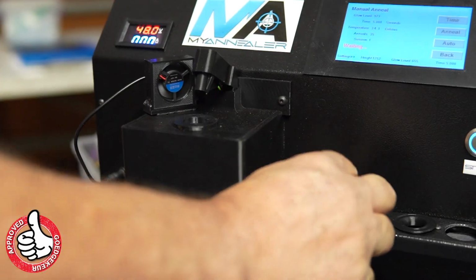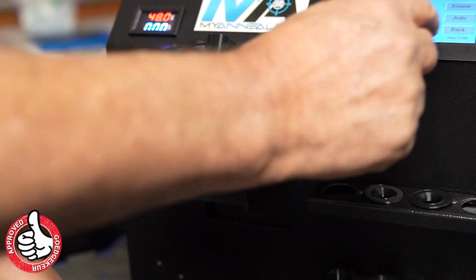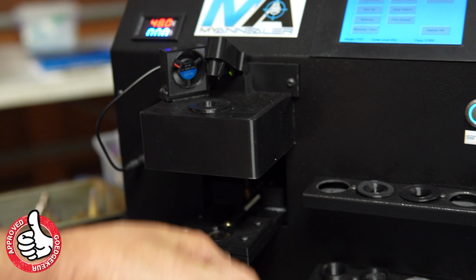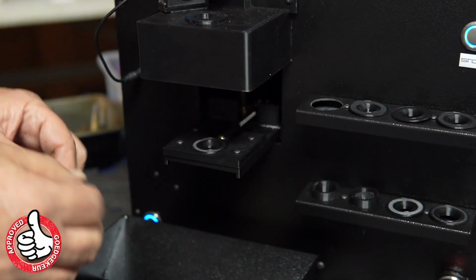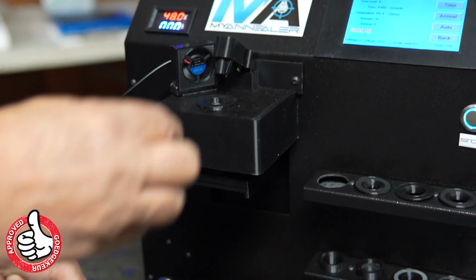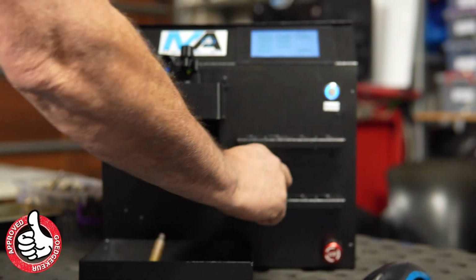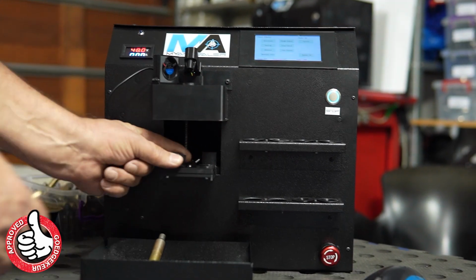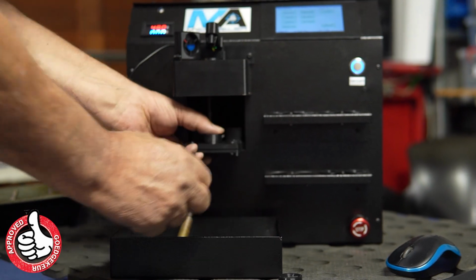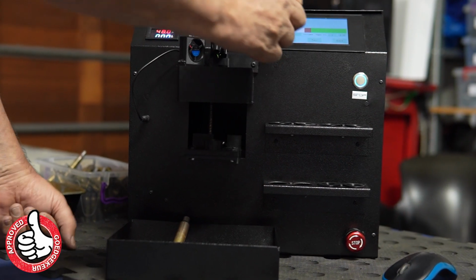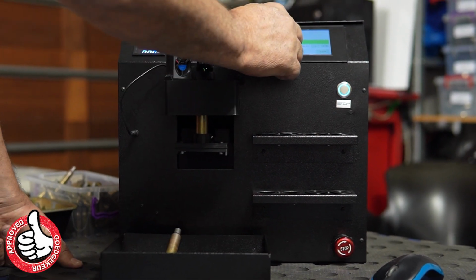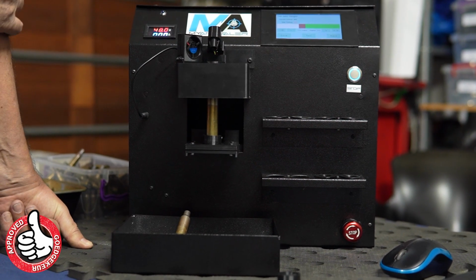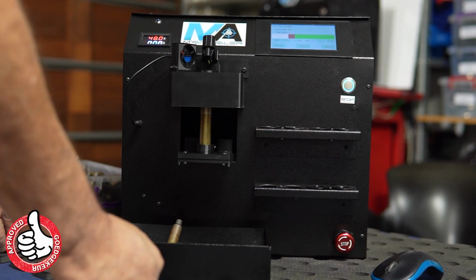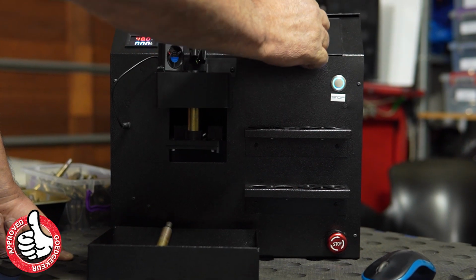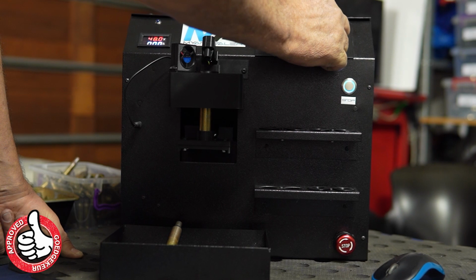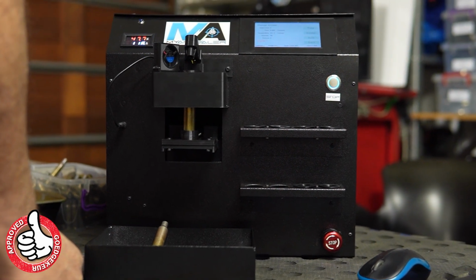C26000 material, what you would typically find is copper at 72% and zinc at 27%. Also keep in mind that there are other impurities or fillers in between in very small percentages, and that makes a big difference. Norma, for example, you would find 77% copper and then the zinc relationship to that. Federal, for example, pushes high levels of copper at 78% and zinc somewhere in the region of 20% with a number of other fillers. So it is clear and practical to understand why from brand to brand, batch to batch, and even from case to case, the correct or the ultimate annealing exposure time has to be intelligently managed in order to give you the perfect level of annealing.